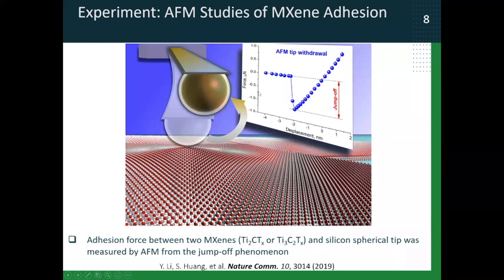So what happens is this: when your tip approaches your material, of course, there are van der Waals interactions and other interactions which result in adhesion between the tip and your material. And then when you try to retract your tip, as shown here, so this is the state at which your tip is in contact with your material, then you try to retract your tip. But it requires force, okay? It requires force that is larger than 0 because you have to overcome this adhesion. And then eventually, if you keep increasing the force, retracting force, at some point your tip just jumps off your material. So this dip corresponding to jump off phenomenon can be used to measure the adhesion force. So this is basically the magnitude of the adhesion force between your tip and your material.